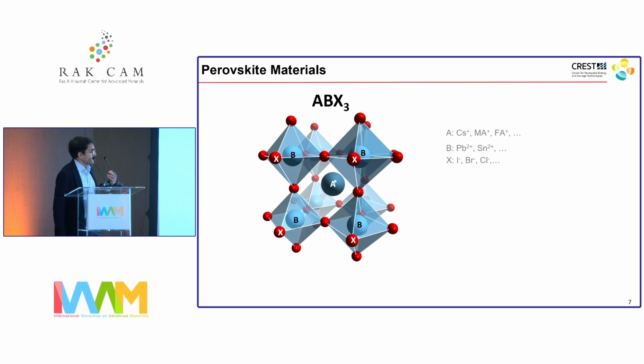Silicon is a single element material, but perovskite is an ionic compound. There are at least 3 components involved. So perovskites have this ABX3 structure, where B is in an octahedra surrounded by X. Typically A can be a cation such as cesium, methylammonium or formamidinium, so it can be organic or inorganic. B is usually lead, but increasingly we're seeing tin being introduced. The X is the halide, and it could be iodide, bromide, or chloride.